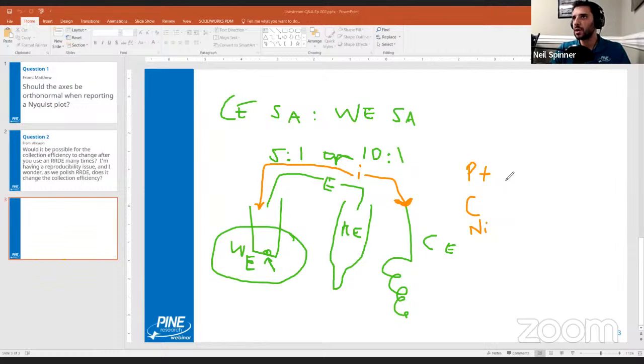Some of those reasons are that in aggressive situations over time, there have been some studies in the past where some people have noted that platinum can migrate over periods of time from the counter electrode to the working electrode. And if you don't want to have platinum contamination, you want to avoid using platinum. And then there are other reasons, it depends on if you're doing non-aqueous or aqueous. There's a lot of systems, right? And some systems are just not as compatible with certain metals. They might dissolve or they might be unstable, things like that. So it can be highly system dependent.